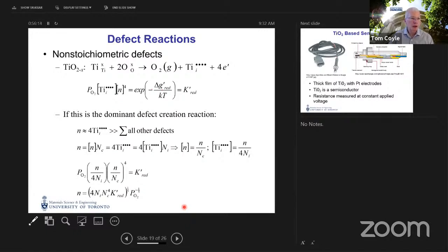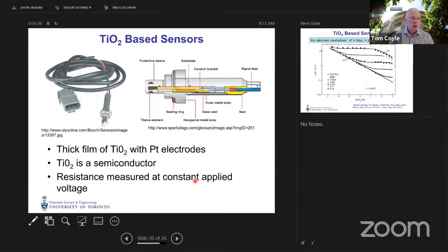Okay, so where are we? In titanium oxide, we have a relationship between the number of electrons in the conduction band and therefore the conductivity and the oxygen partial pressure. We don't know which relationship is correct, but we can expect that the conductivity will depend on oxygen partial pressure. So let's do some experiments. We'll make up a TiO2 sample, put on electrodes that allow us to measure the conductivity.